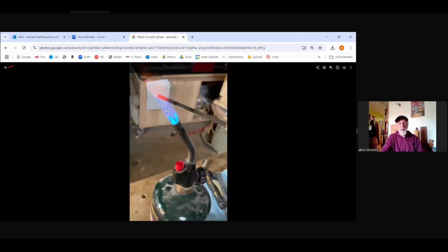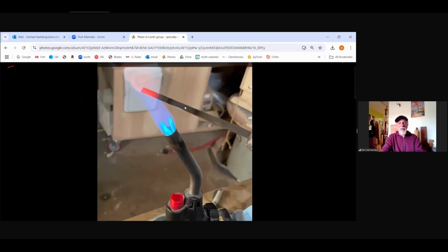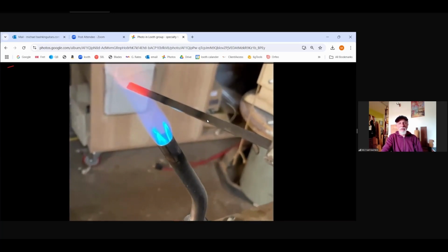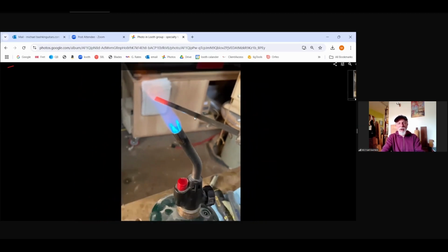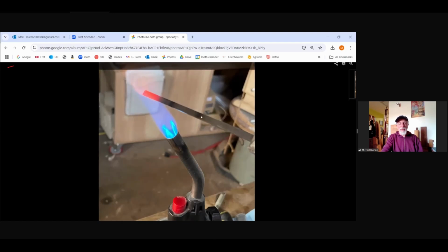So here's the propane torch. General rule of thumb is when the tip of the tool turns cherry red, you just want to hold it there for less than a minute, but probably more than 30 seconds. And that's just to make sure that the steel is heated evenly. And you can see over here, there's some different color bands going on, and these actually represent some different temperatures. Down here, it's really hard to see in this photo, you just have to take my word for it, but it gets to kind of a yellowish brown, and that would indicate the color we want to try and achieve with the tempering.